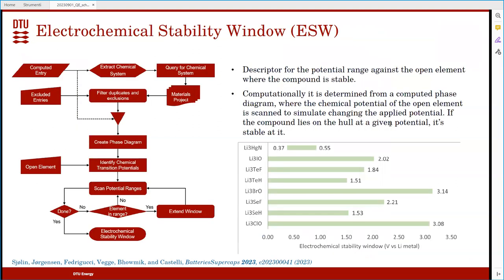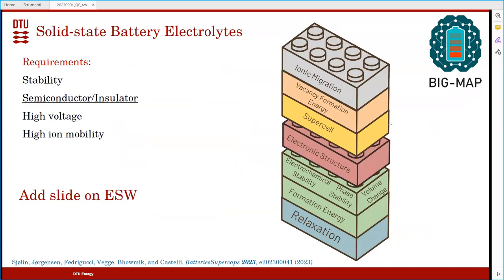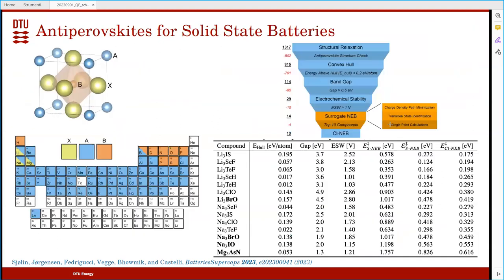Basically, you take the structure from the Materials Project and you calculate the potential where your electrode or electrolyte is stable. And you get to something like this. This was done for the antiperovskites for solid state electrolytes. Then you can see that most of these are actually stable until about 1.5 or 2 volts versus lithium metal. And this is all autonomous, right? And it can be integrated into what you had before. Again, the output becomes the input, right? So you try to concatenate everything. And this is basically the screening that we have run.